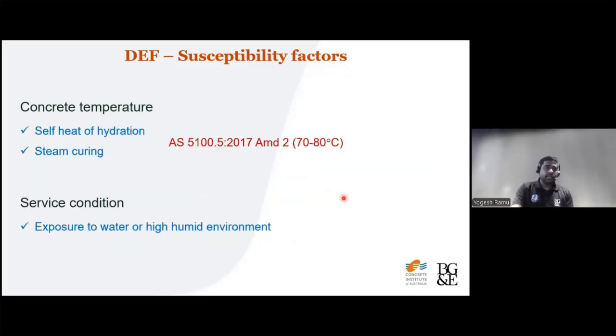As I mentioned earlier, concrete temperature, either due to self-heat of hydration or steam curing, can be problematic. That's why this amendment restricts the temperature here to 70 to 80 degrees Celsius. And then the service condition: if you remember the earlier example that I showed you, the concrete was touching the water. So exposure to water or a highly humid environment can lead to expansive DEF just by promoting leaching of alkalis from the concrete, at least in the cover zone.